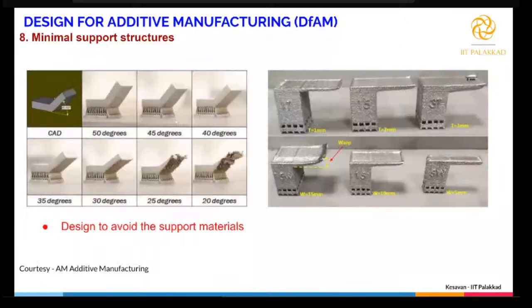For example, as I said, if the inclination is less than 40 degrees, then I need to give the support. You see, as I decrease the inclination, the material is collapsing. To avoid this, I need to give the support structure. It is the same as what you're seeing on the right side. With overhangs, if it exceeds the limit, you can find there is warping, so it won't meet the dimensional requirement. You need to account for all these things in the picture.